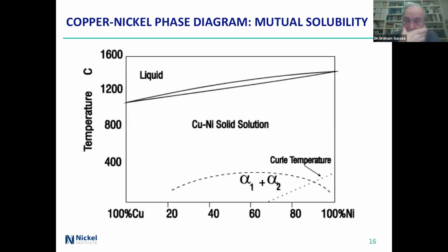This is the reason why copper-nickel alloys are fairly easy. Copper-nickel is a solid solution - they're basically completely soluble in each other, so there's no problem with bad phases coming out of that. It's all in the other things that are in there. So you go from a liquid, you've got a bit of a band there, and then copper-nickel solid solution, totally soluble both ways. The reason why they tail off at the ends is just because it drops down a bit when you get to almost pure copper, almost pure nickel.